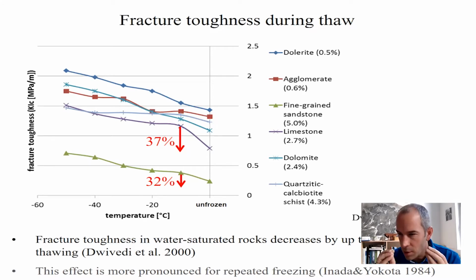Visualize I'm the rock slope failure that wants to fall down. At my back I have 10 rock bridges. Okay, and then I start to warm, and suddenly all the 10 rock bridges at my back lose 37% of their fracture toughness. And then it's quite likely that one of these 10 rock bridges that keeps me in position, rock bridges are intact rock connections from me to the rock face behind, can no longer take my load. So the shear stress I put on it is too big and it starts to fracture because it has undergone a 37% reduction of fracture toughness.